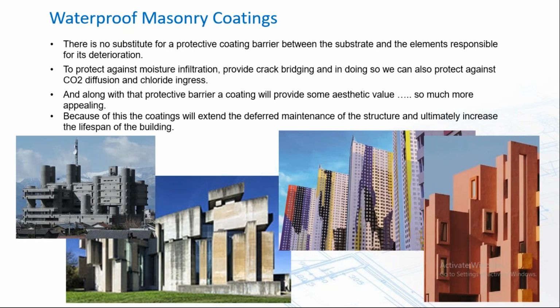But then we get to my favorite, masonry waterproof coatings. And in my view, there is actually no substitute for a protective coating barrier between the substrate and the elements responsible for its deterioration. Protect against moisture infiltration, provide crack bridging, and in doing so, we can also protect against CO2 diffusion as well as chloride ingress. And along with the protective barrier, a coating will provide some aesthetic value. And it's just me, but it's so much more appealing than just uncoated gray concrete. Because of this, coatings will extend the deferred maintenance of a structure and ultimately increase the lifespan of a building.